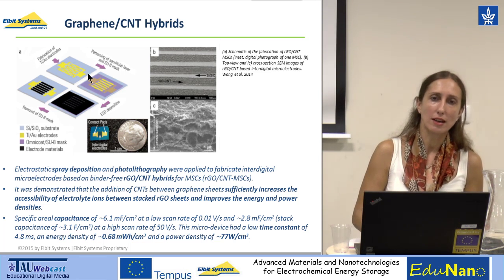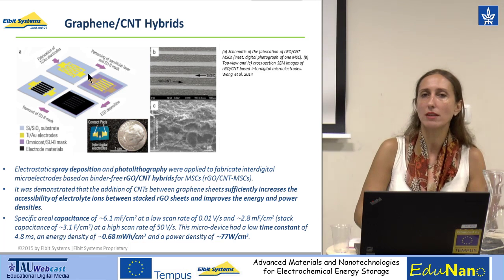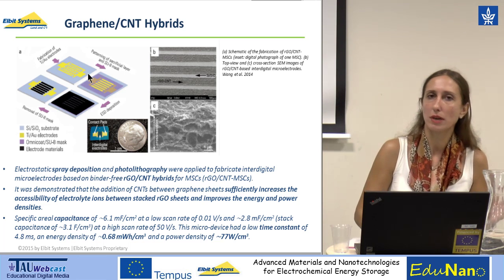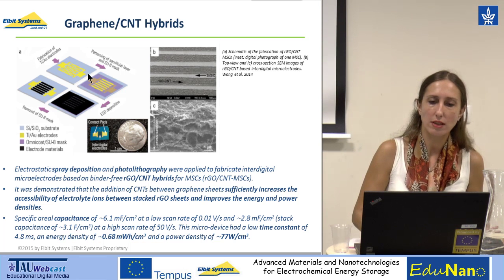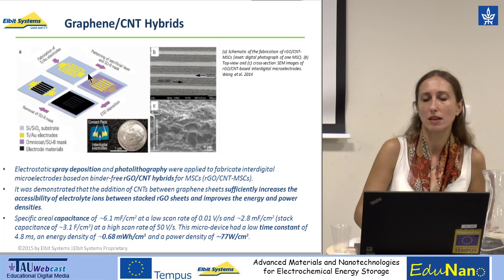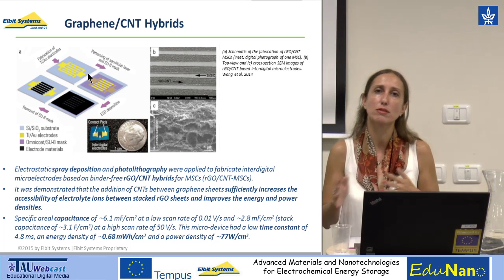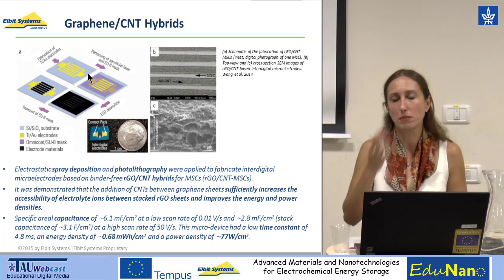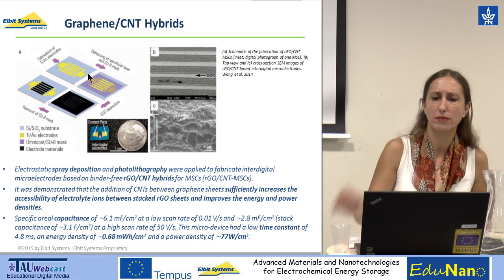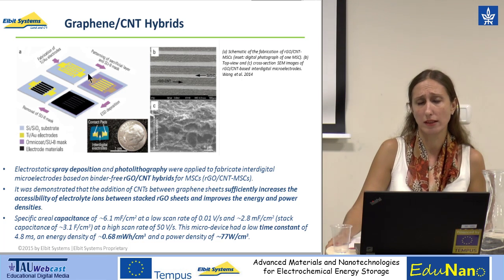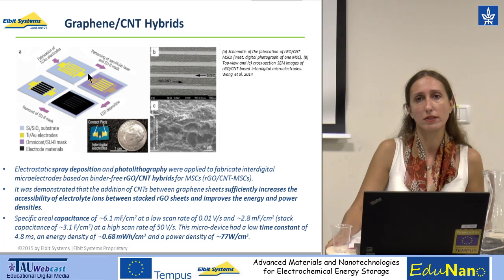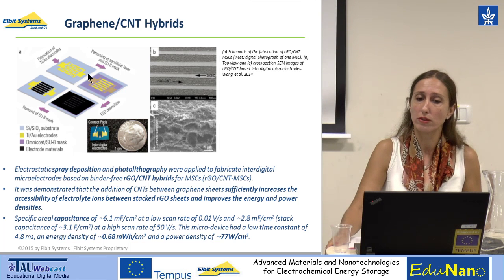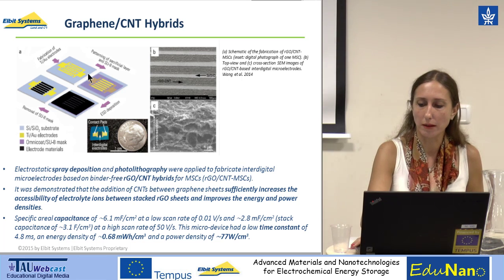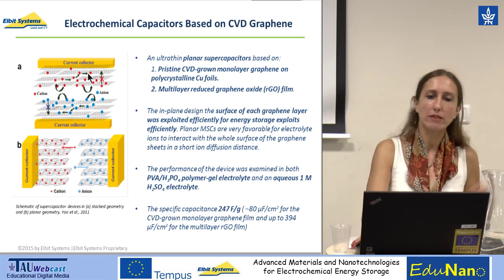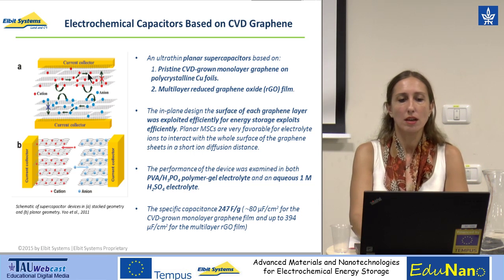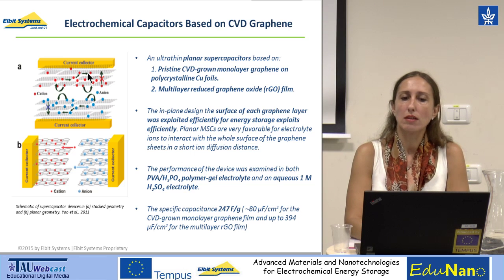What we talked about now are actually values that we were not familiar with before. We are talking about values of orders of magnitude, but please take into consideration that we are talking now about microelectrodes. When you compare these kind of microelectrodes to what you have today in the market, usually done by either ceramic, thin plates of ceramic oxide material like titanium oxide, etc., these are very, very large values. These are values higher by an order of magnitude in comparison to what you have today for commercial micro supercapacitors.